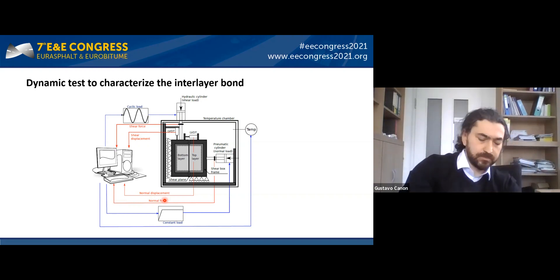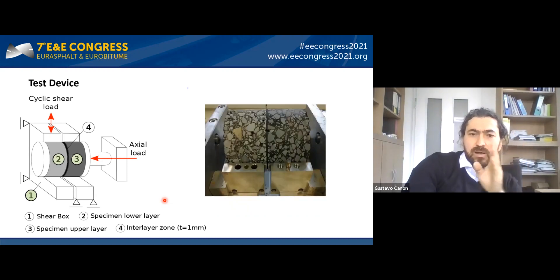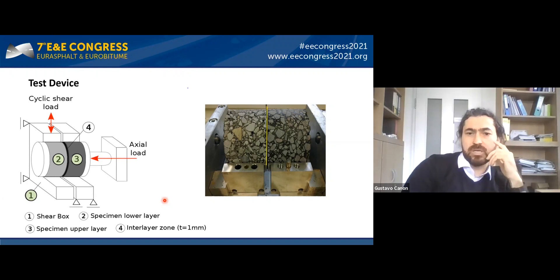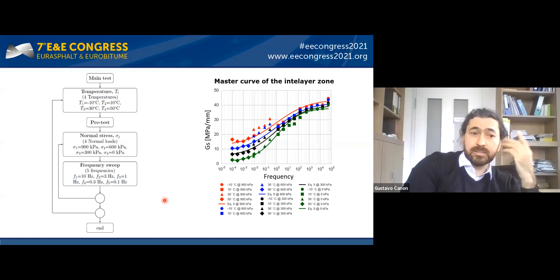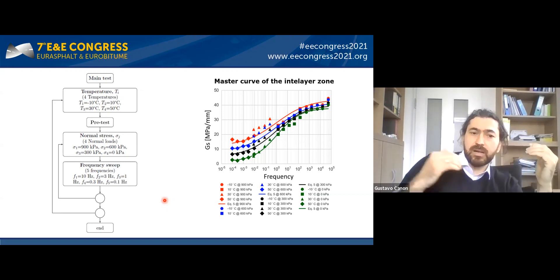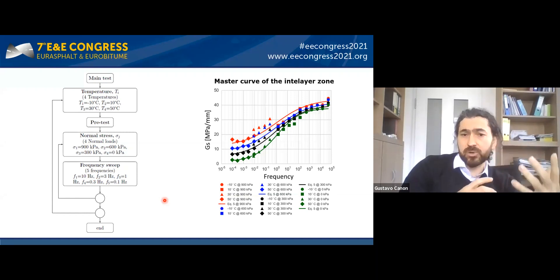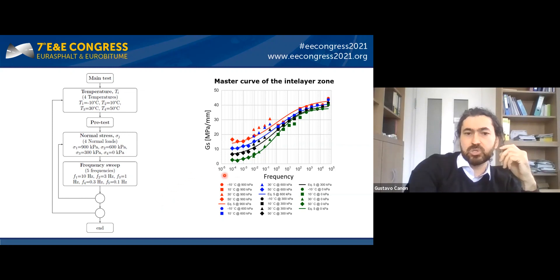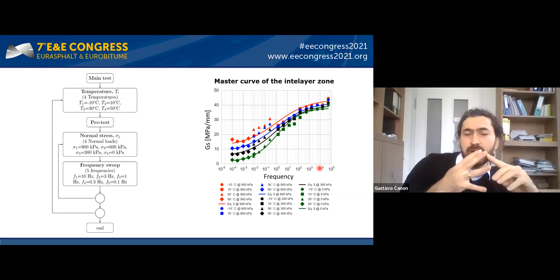The test specimen consists of a two-layer specimen introduced into an adapter, with the interlayer bond clearly visible in the gap between the two parts. The test is done at four different temperatures, at different normal stresses from 900 kPa down to 40 kPa, and at different frequencies. The results are master curves of the interlayer area — shear stiffness as a function of frequency, temperature, and normal stresses. These master curves are then introduced into a mechanistic pavement design using interface elements.